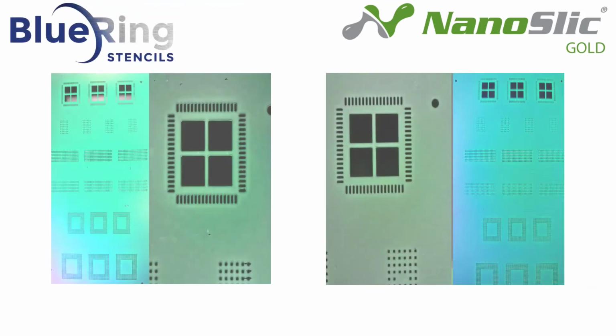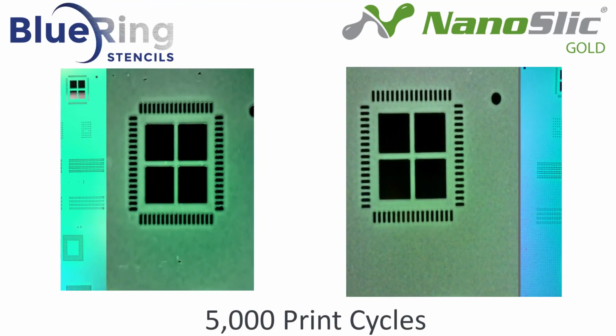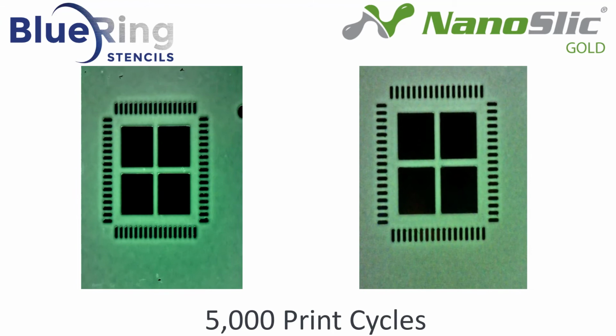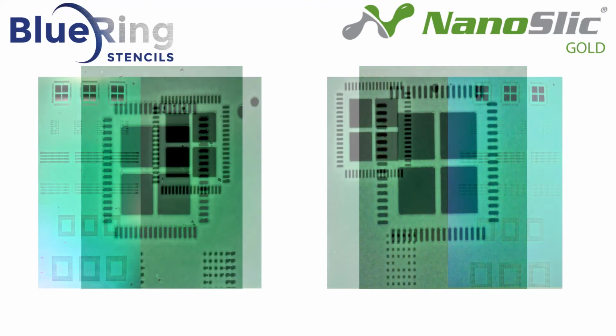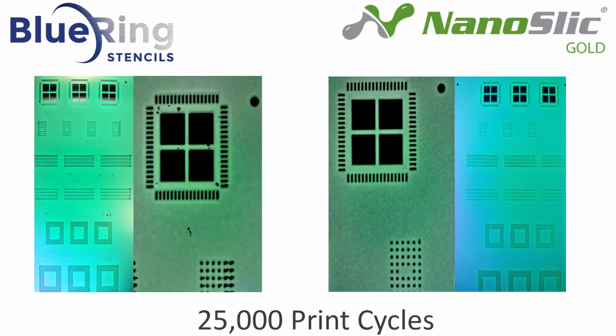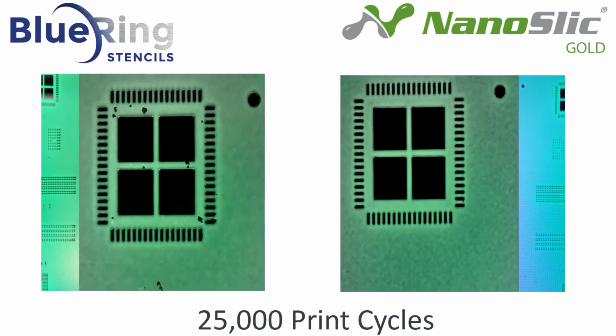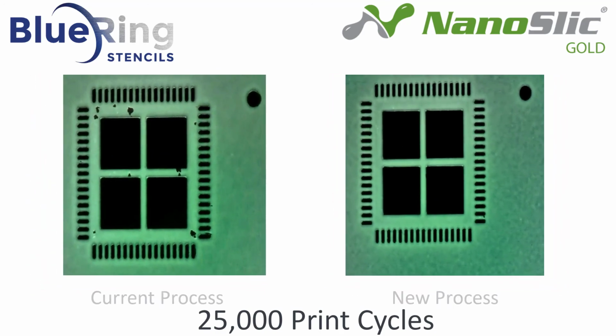How did this new coating hold up in our print simulator? Let's take a look. These first images are taken after 5,000 print cycles. You can see a few chips in the current process image and none in the new modified surface coating. Again, looking at images of the same stencils after 25,000 prints, you can see even more chipping on the current process images, and the modified surface coating still looks brand new.